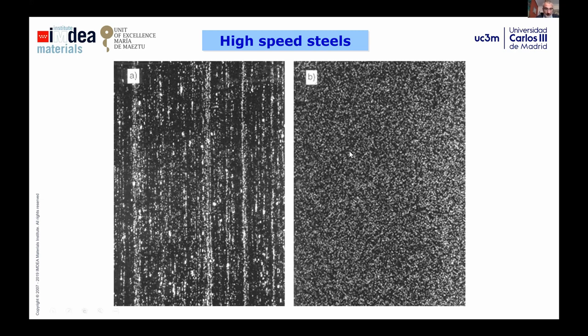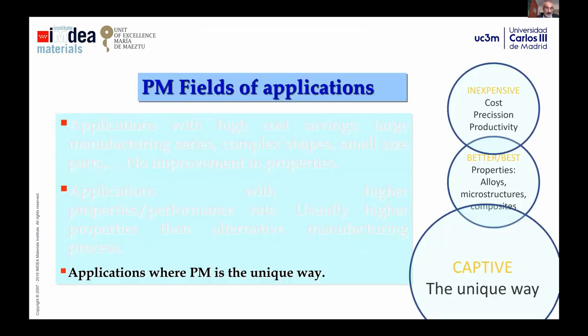And if you compare on the right with the powder metallurgy microstructure, you have much lower size of the carbides, much better distributed, without any directionality of the carbides, and all these microstructural features allows that this kind of high-speed steel produced by powder metallurgy is much better in properties than any other produced by forging or other alternative. So this is the case of the second niche, the second field of application. And we can go to the third one. The third one is the captive way.